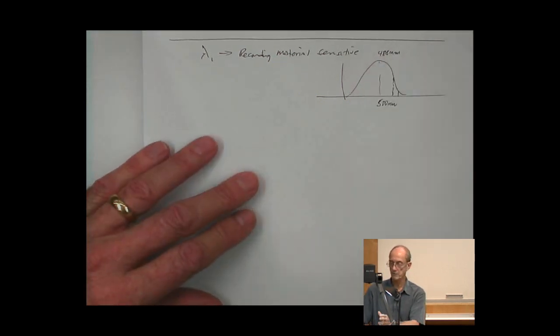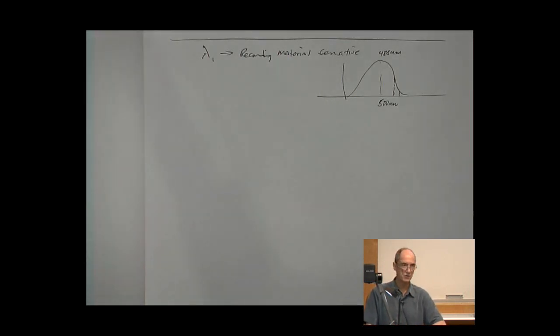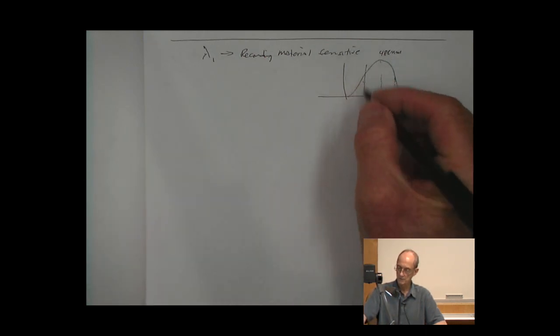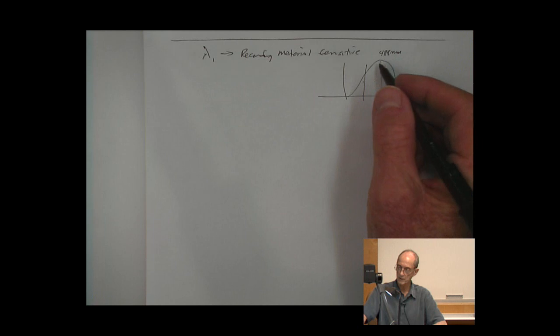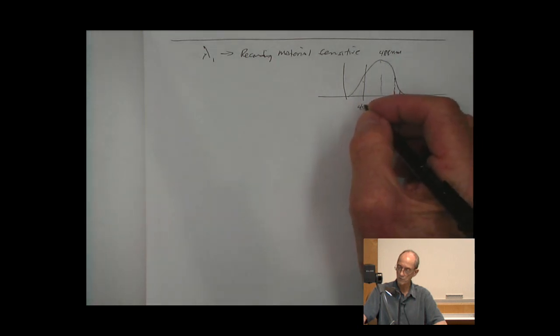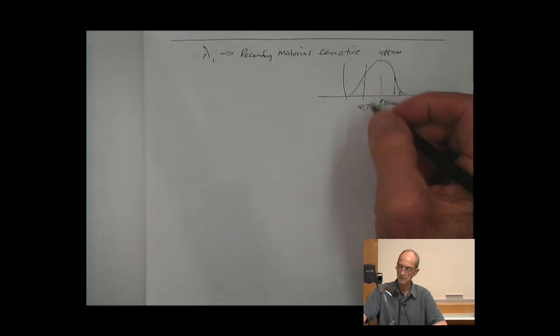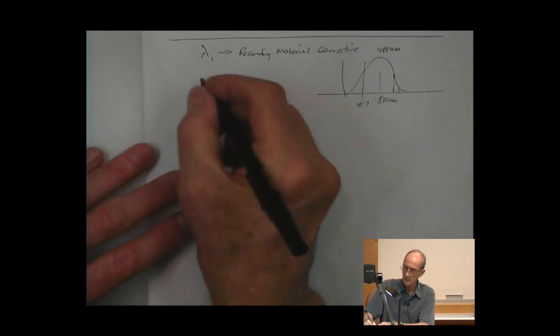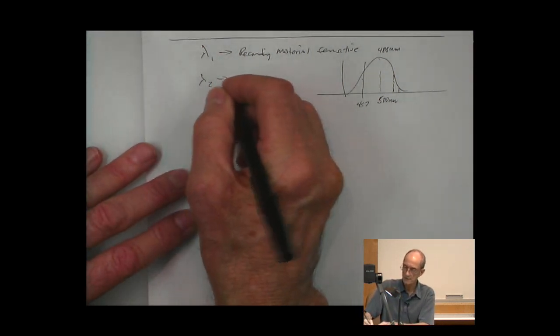So argon, that's why holographers like to use argon lasers, because we have these lines that pretty much cover lots of materials. If you have a photoresist, the sensitivity falls off. You can't even use 488, but there is a 457 line in the argon laser, and there's also a diode pump solid state laser that produces a 457 nm. So there are some lasers now that can operate there, but the problem is a lot of times you want to use it at a different wavelength.